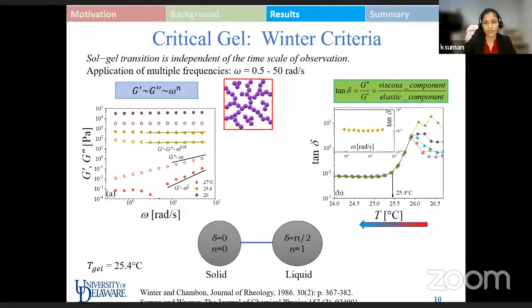So if we have a soft matter system which is undergoing sol to gel transition with this critical gel transition, and we have measurable properties of zero shear viscosity, equilibrium modulus, we should be able to validate all these scaling laws. So right now I showed only for one kind of system. I have also done it for a polymer system, which is a system of polyvinyl alcohol, and which undergoes thermoreversible gelation, and that is also very nicely obeying all the scaling laws.